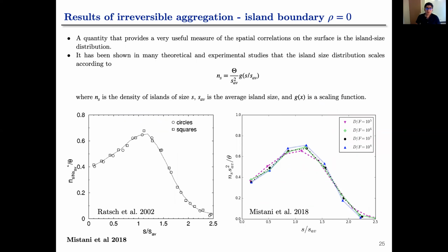Now, besides the efficiency of the method, there's also the issue of accuracy. You test that because every time you run the simulation, you get a different morphology. It's a statistical test, which is a kind of benchmark for these kinds of simulations. You basically compute the surface area of these islands and normalize them according to some function, and it has to fall into this universal distribution, which should be independent of the parameters of the simulation. So no matter what the diffusion coefficient or the flux of the depositing atoms is, you should always get the same thing. And actually, they all collapse on each other, all of our simulations.